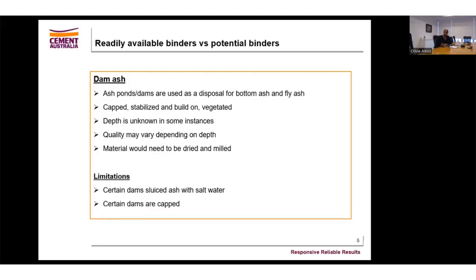Some limitations to the use of dam ash: one in particular is that some dams have sluiced the ash from the power stations to the dam with salt water. This would be quite detrimental if we're looking at the chloride percentage. And some may say you can just wash the dam ash in order to reduce that chloride percentage. But when we're going back to what is a more viable alternative binder, we want to reduce our investment costs.